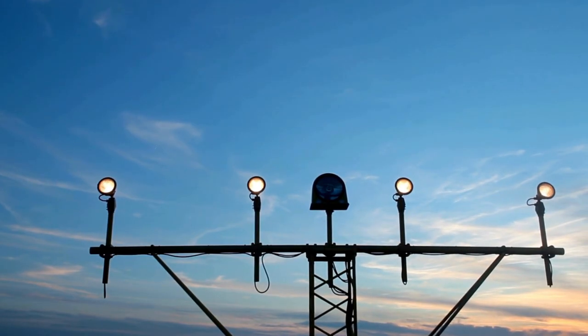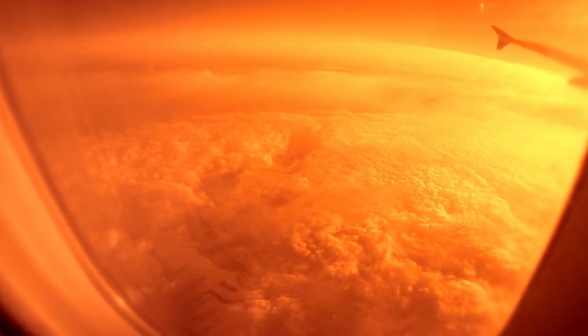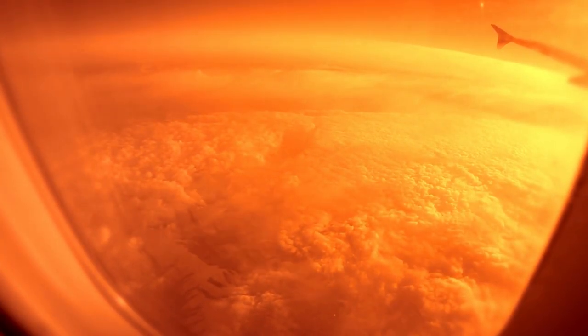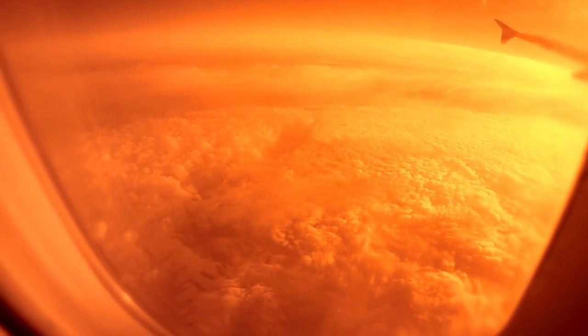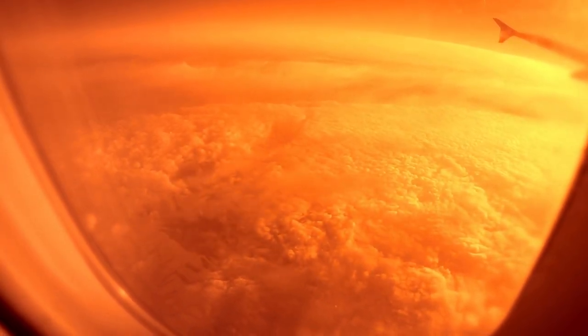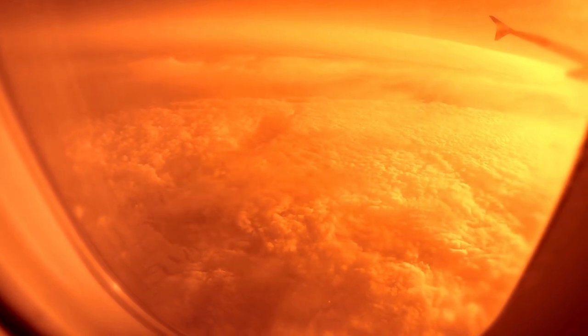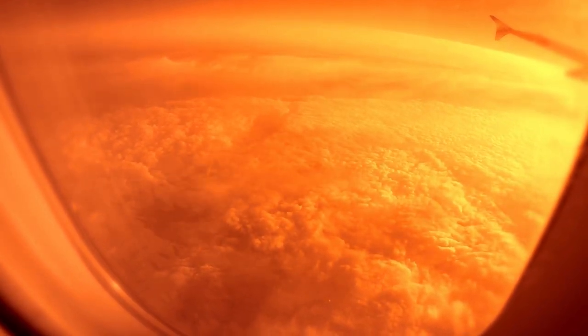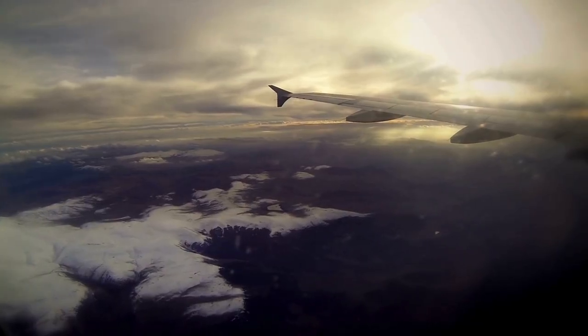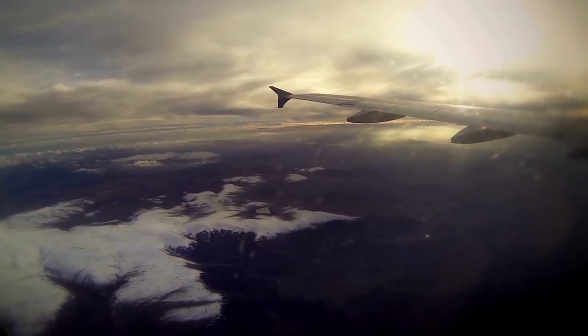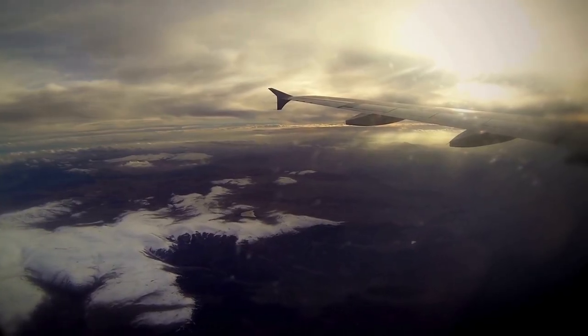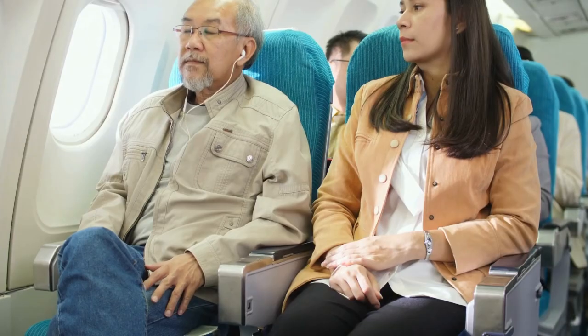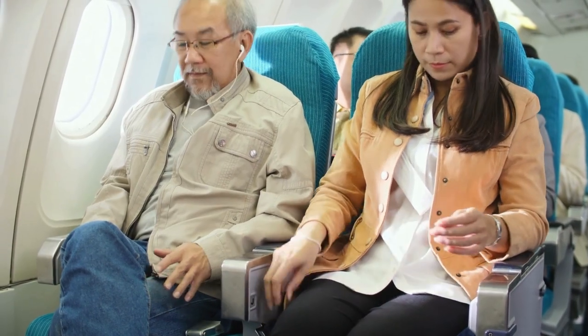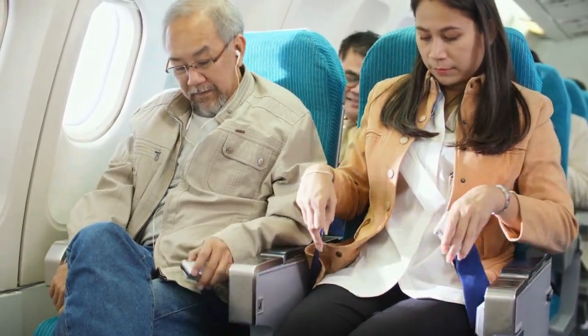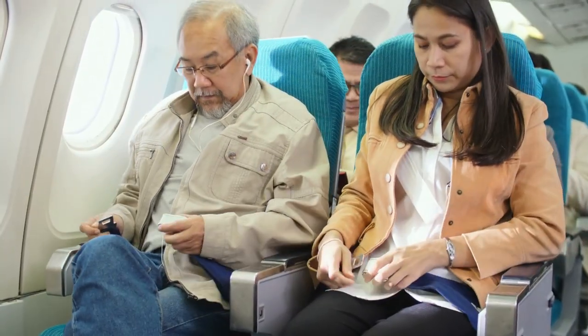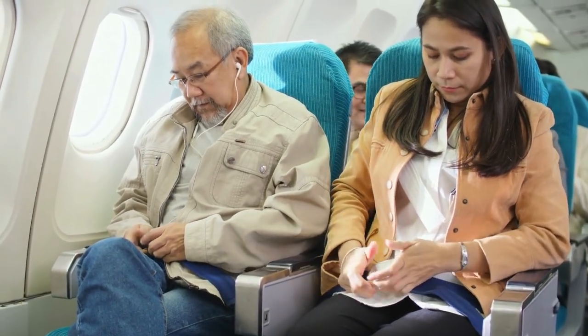The Airbus A380 introduced an additional layer of complexity in this area. Its upper deck extends the full length of the fuselage, creating a double bubble cross-section rather than the single circular or oval section used on conventional aircraft. The stress distribution around window cutouts in a double bubble fuselage differs from that in a conventional section, requiring specific analysis and testing to verify that the rounded corner geometry provides adequate protection against fatigue initiation at the actual stress levels present in that specific structure.